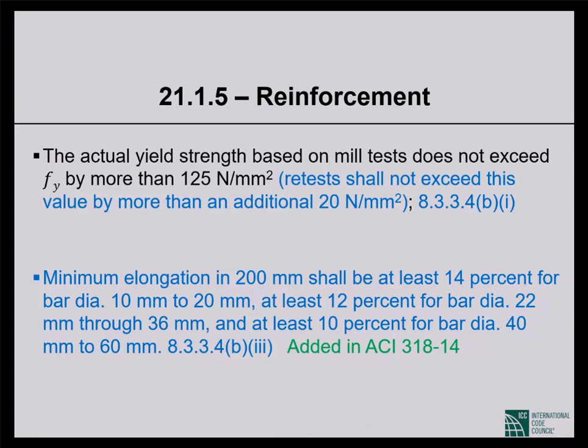This is important because in seismic applications, more is not better. If you have higher yield strength in your reinforcement than you specified, the member reinforced with that steel will have higher flexural strength than you counted on. That member will attract higher shear forces to itself in an actual earthquake situation. You will not be correspondingly increasing the shear strength of the member, thereby making brittle shear failure more likely. And that is not good. Okay, so this is why this is an important requirement.